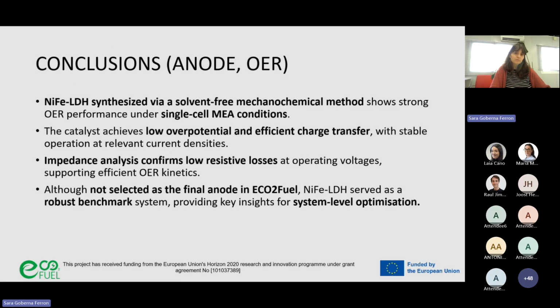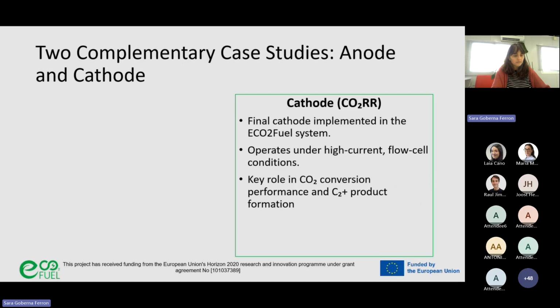So as a conclusion from this example of this anode catalyst, we demonstrate that nickel iron LDH synthesized by a solvent-free mechanochemical method shows a strong oxygen evolution performance when tested under single cell MEA conditions. Although this catalyst was not selected as the final anode for the CO₂ fuel system, it was a robust benchmark system, providing valuable insight that supported system-level optimization. So now I will move to the cathode side.